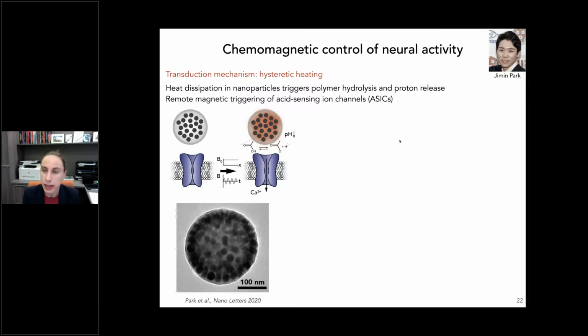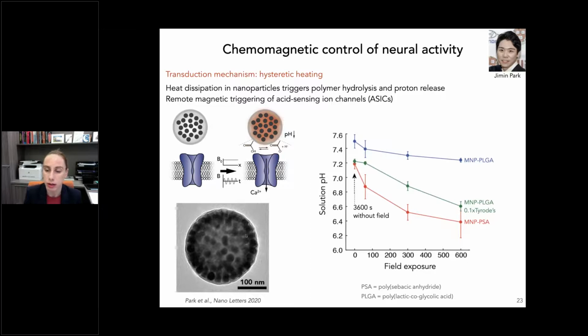And there are many pH-sensitive ion channels in biology, the key class being acid-sensing ion channels, also known as ASICs. In this work, led by a talented student, Jimin Park, he has developed polymersomes that incorporate magnetic nanoparticles of iron oxide together with either polylactic-co-glycolic acid or polysebacic anhydride. You can see that depending on the chemistry, we can tune the decrease in pH in response to magnetic field exposure. Polylactic-co-glycolic acid responds very slowly, since polymer hydrolysis doesn't have a very high rate at the temperatures that magnetic particles can deliver in a magnetic field. But PSA, polysebacic anhydride, has relatively quicker kinetics, allowing us to control pH locally.